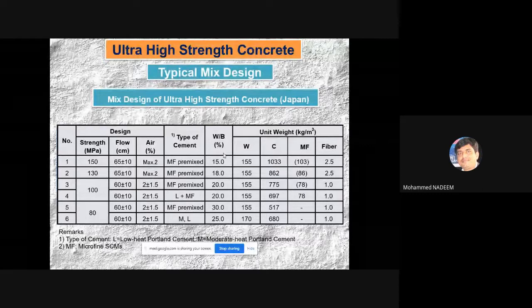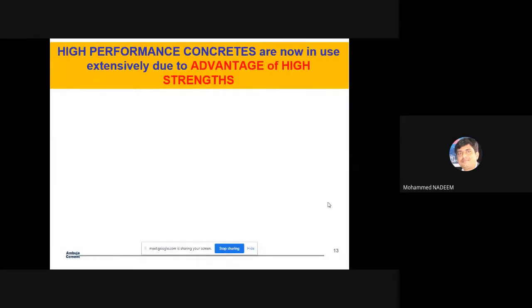Just see the water binder ratio of less than, say, 0.15, 0.18, 0.2, 0.25, 0.3. Now the water cement ratio or water binder ratio is being restricted to less than 0.3, because the ultimate idea is to reduce the porosity in concrete, meaning fine pores. Once you are reducing the fine pores, naturally you have to reduce the water binder ratio. And nowadays a lot of good PC based admixtures are available, where you can reduce the water quantity by more than 30, 35, 40%. And of course cement and microfine material are added, and sometimes fibers are also added. So you will get very high strength concrete with utilization of these materials.